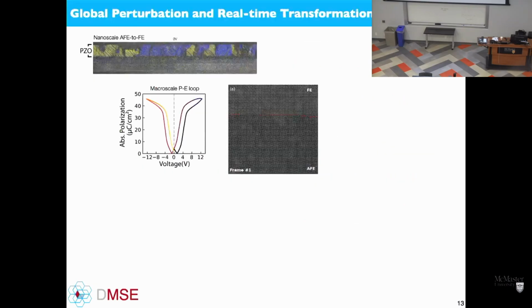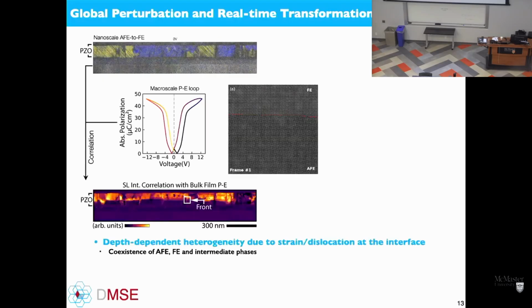Partly it's because, again, this film doesn't fully transform. So you're always getting a mix of those phases within the sample. And a macroscopic paraelectric, a PE loop, goes through there, you get some shift going across the boundary. But one thing that we found is that the region near the interface, the reason it's dark here, is because it's not transforming at the bottom layers of the film. It's only the top half that's essentially transforming as a function of bias.